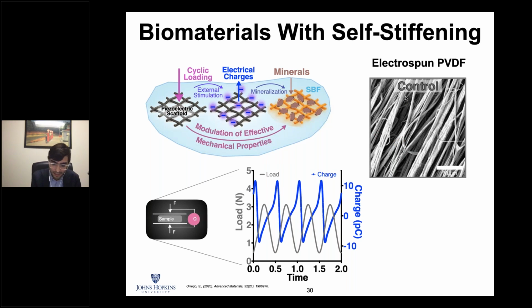We submerge this into these saturated fake blood, calcium-rich solutions, and then we apply force for a long time, 7 days, to activate the charge. Then we let the charge drive and bring all the calcium to the scaffold and deposit.